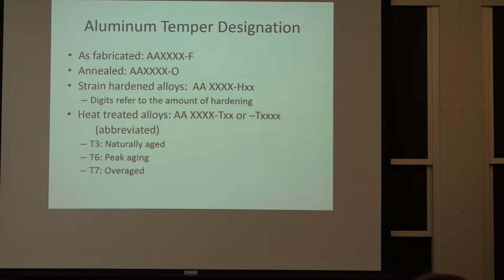And so you take advantage of the low yield strength for formability, and then it gets harder from the action of work hardening, but mostly the formation of the precipitates at the higher temperature, and it is improved by the deformation. So essentially creating all these dislocation networks during deformation helps with the formation of higher strength precipitates for hardening by precipitation.